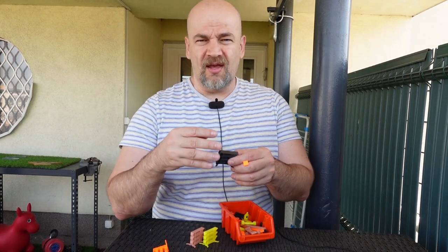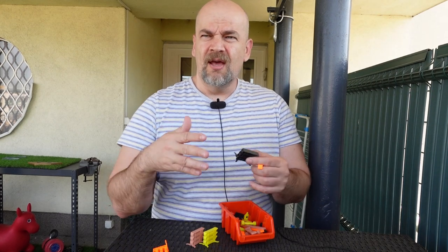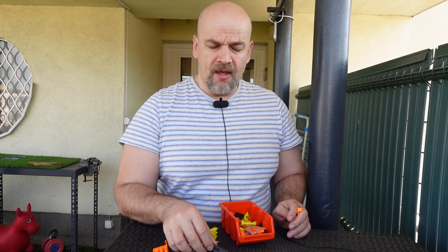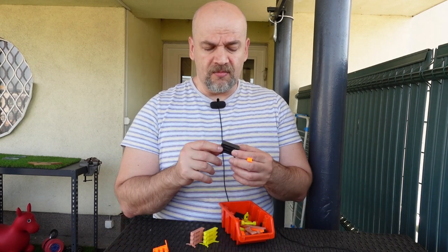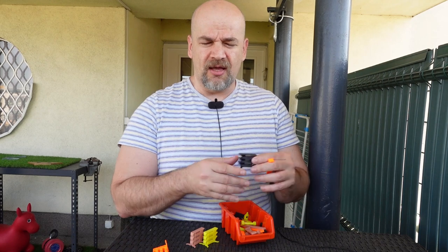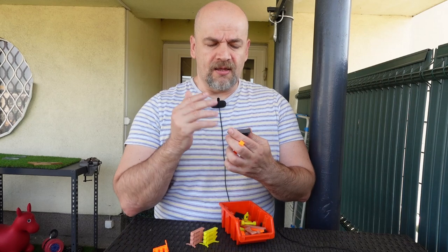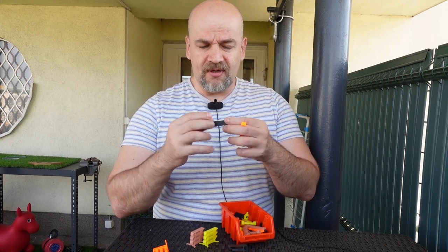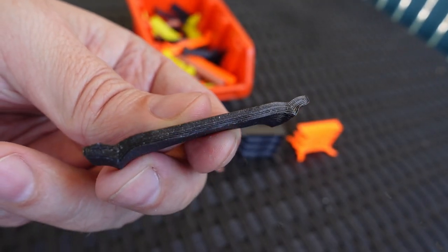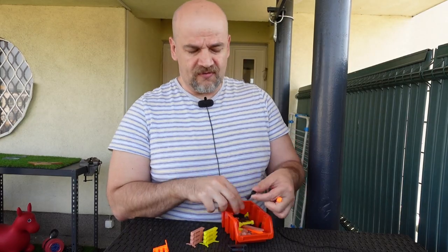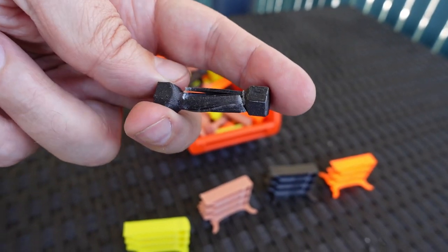The next step is the ABS. Actually ASA in this case, but they are very similar materials. ASA is UV resistant, it's quite a good material. It's actually lighter compared to the PLA and PETG, lower density. I was a little bit disappointed with the weak layer adhesion. I can see some layer separations on almost any kind of specimen, or maybe even on this twist test. But yes, it can resist temperatures almost up to 90 degrees Celsius.